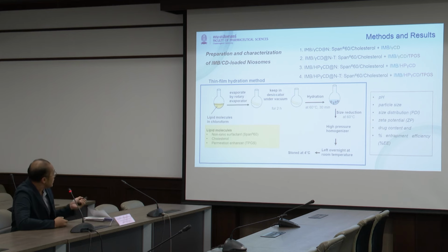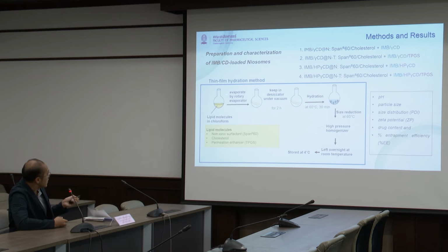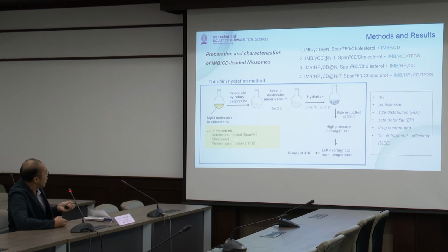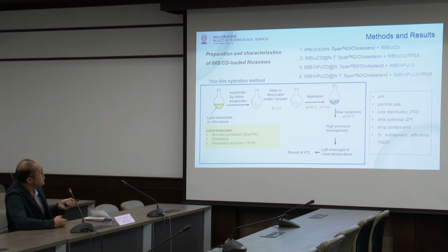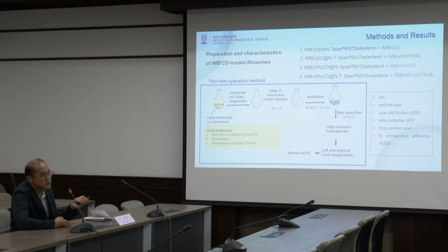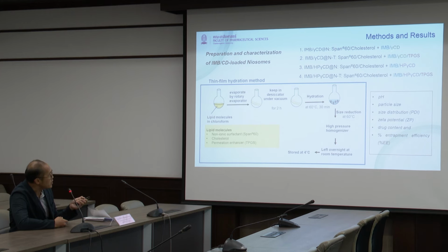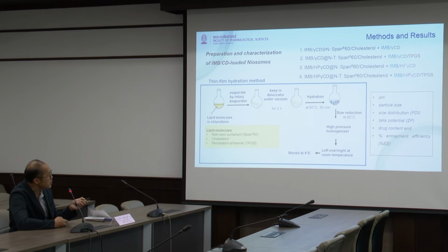And now shall we go to the preparation of the niosome. We use the thin film hydration method. All materials are dissolved in chloroform and then kept in a desiccator after evaporation. And then we use a hydration medium composed of imatinib and cyclodextrin. We have four formulations according to the gamma cyclodextrin and the HP gamma cyclodextrin, and also in the presence of TPGS. TPGS is like a penetration enhancer for our hypothesis.